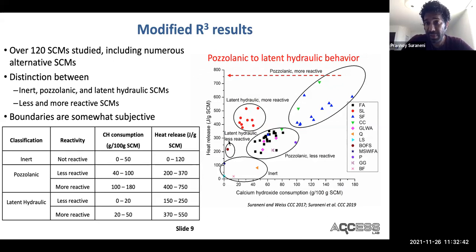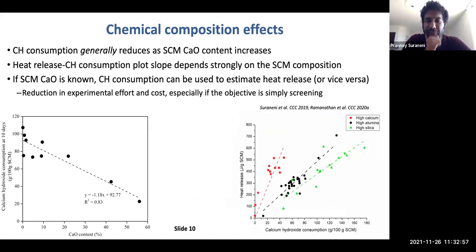With the classifications that we've seen, you can really see that the slag is behaving completely differently from all the other materials in terms of its heat release versus calcium hydroxide relationship. Now, when we look at chemical composition effects, we have to be careful here because I'm talking about bulk chemistry. And I've already mentioned before that it's amorphous chemistry that's actually important. But of course, the amorphous oxide content can be a little bit difficult to determine. So I discussed just the bulk chemistry here, but we show that the calcium hydroxide consumption reduces as the CaO content increases. And this relationship is reasonably nice.